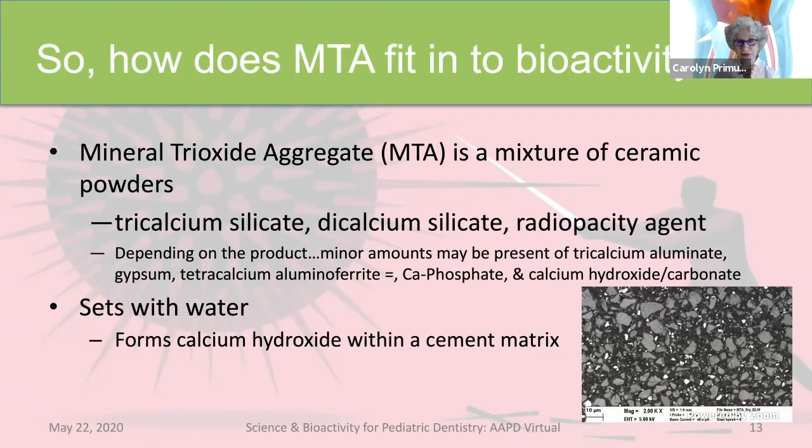So let's go back now that you know that MTA can be known by several different names and see how it fits into bioactivity. As I said, it's a mixture of ceramic powders, tricalcium silicate, dicalcium silicate, and a radiopaque agent. Depending on the material, various things may be included, other ceramic powders, including calcium carbonate. But all of these products are going to set with water. And when they set, one of the reaction products is calcium hydroxide, a well-known bioactive material in dentistry. And you can see it within the cement matrix that's shown over here on the right.